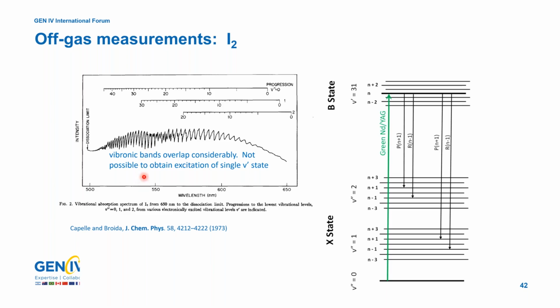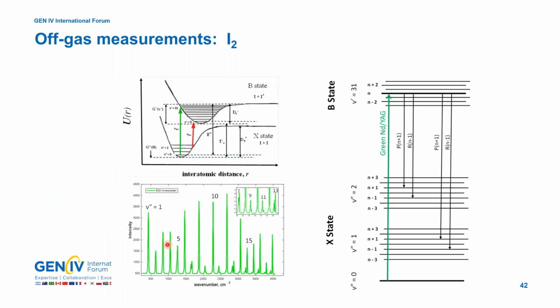We're illuminating at 532 nanometers excitation right on top of a lot of vibronic progressions. So we're shining light and getting into an excited vibronic state, and we get light emitting and nice fluorescence bands coming out into the visible spectrum. This is our fluorescence spectrum. They also have a beautiful vibronic progression. We've measured them all the way up to 20, 25 vibronic progressions in each of our fluorescence spectra, which is really pretty, but it's also very useful.